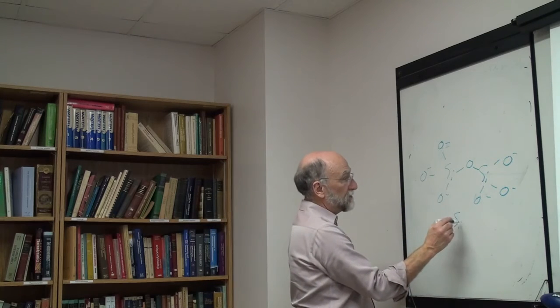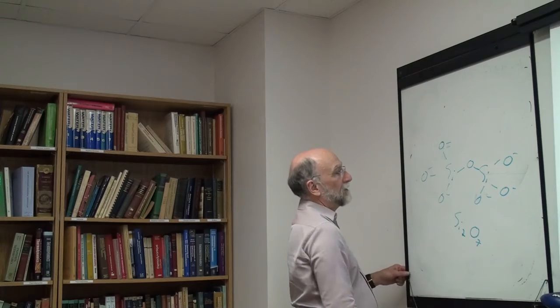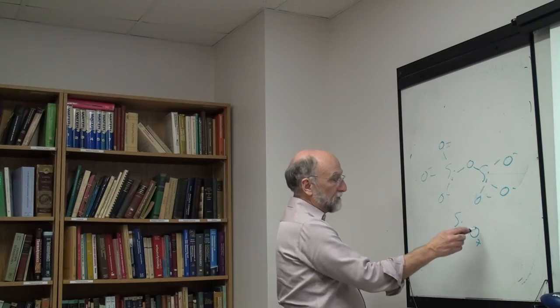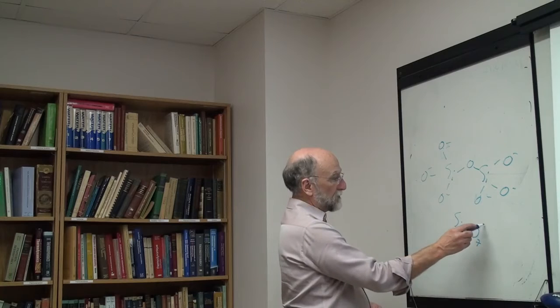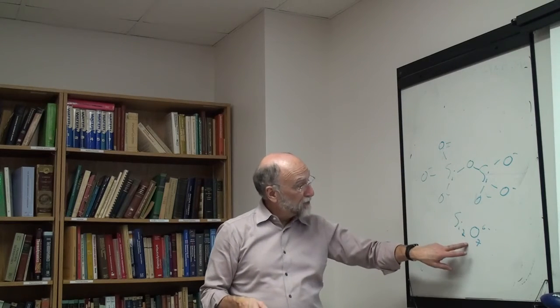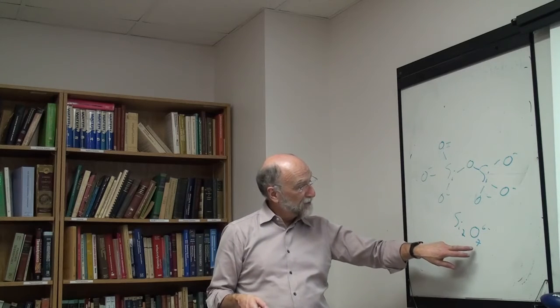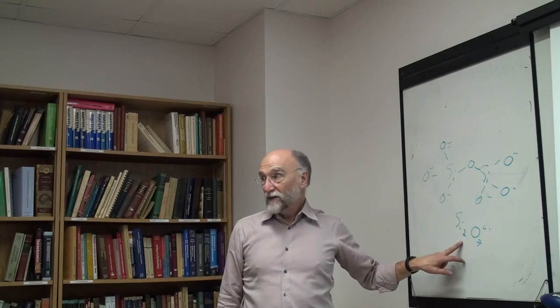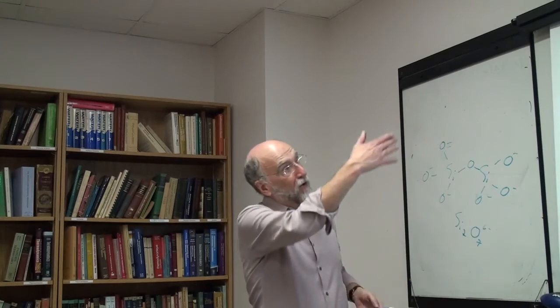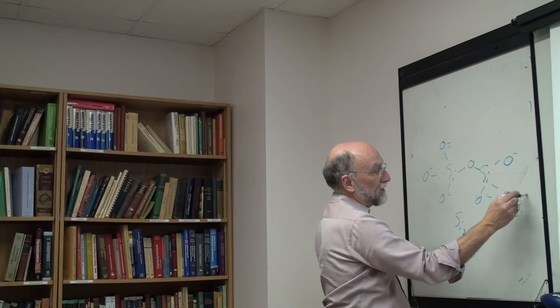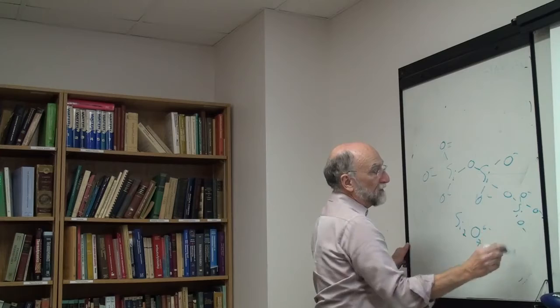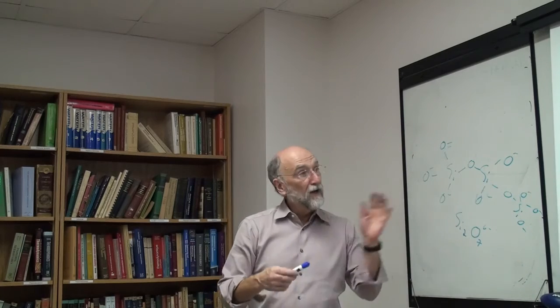So this would be Si2O7, 6 minus. Okay, a dimer. This then reduces the amount of oxygen. You need less now, it's 3.5 oxygens per silicon rather than 4, so you can go over a little bit further. As you go over, add more and more silica, then you start to get more. So you get another bridge here, now you start to get a trimer. So you get a linear chain. You get trimers.